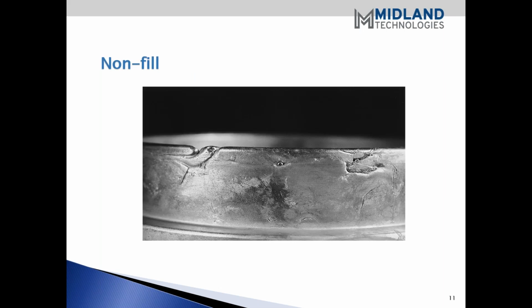This is an example of non-fill. And this is a rim of a casting. You can see that the metal has not solidified. A lot of times this could be due to cold metal as a possibility, but again, it also could be attributed to the fact that you don't have adequate evacuation of the cavity. Next slide.